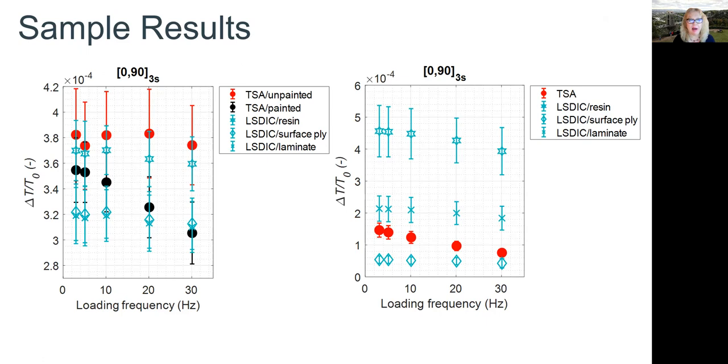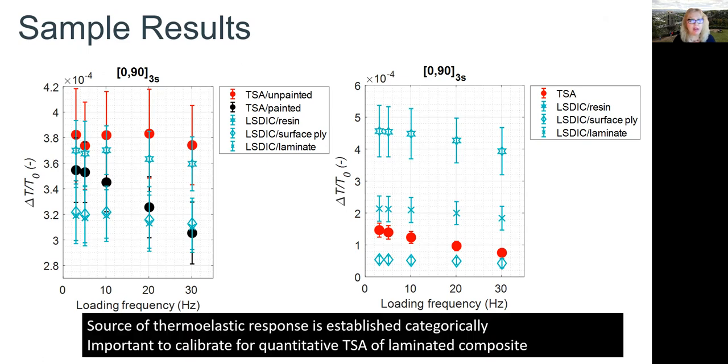So we think now we have established the source of the thermoelastic response categorically, and come up with a calibration procedure that allows you to determine for your particular laminate manufacturing process, fiber volume fraction, etc., how to determine which loading frequency you need to use to conduct tests.